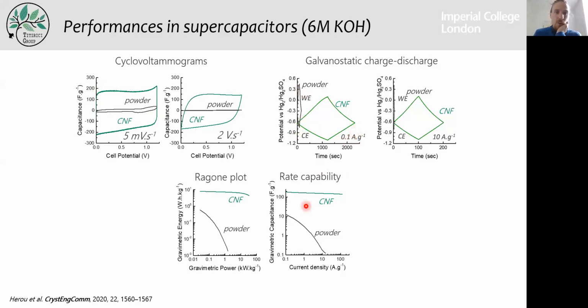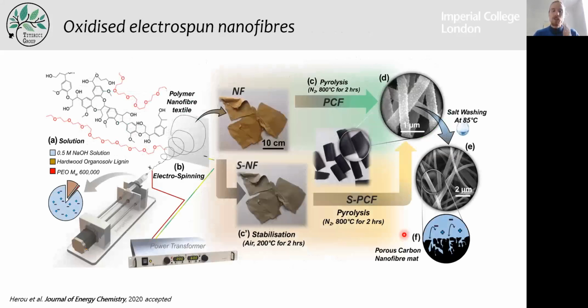If we look at the rate capability, the capacitance of the carbon nanofibers is much higher compared to the powder, which exhibits only 10 farad per gram. That leads to a high energy density for the carbon fibers, approximately 10 watt-hour per kilogram, whereas the powder is really poor. So we tried to improve this system a little by taking basically the same recipe, but instead of doing direct pyrolysis and then salt washing, we submit the mats to air oxidation at 200 degrees for 2 hours, and then we do the pyrolysis.